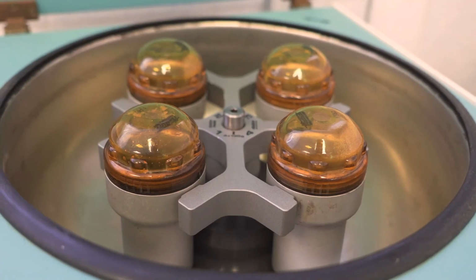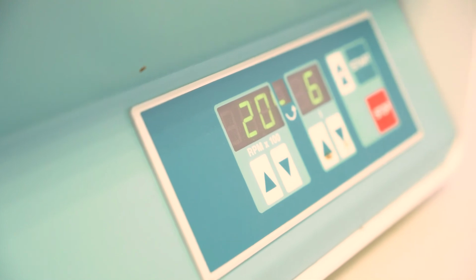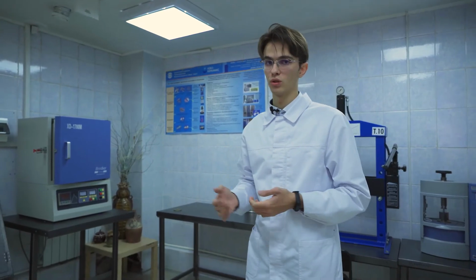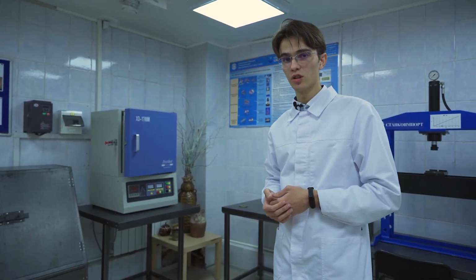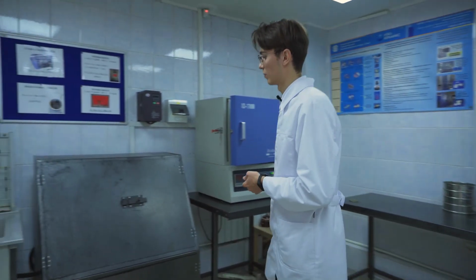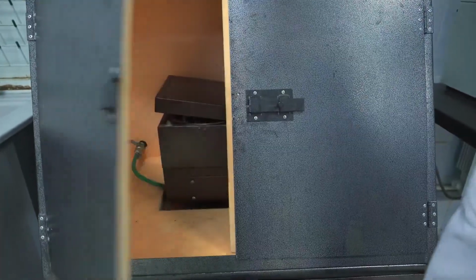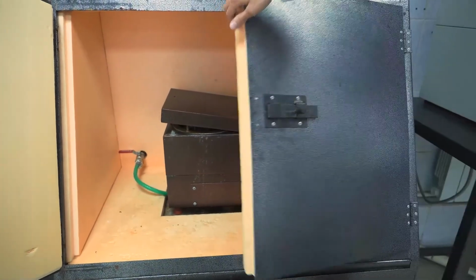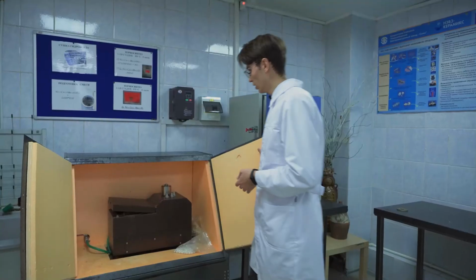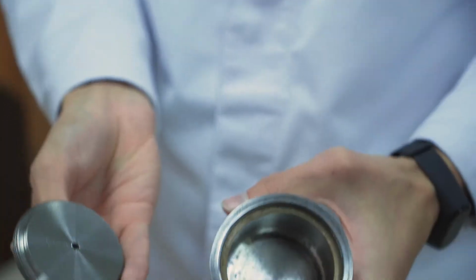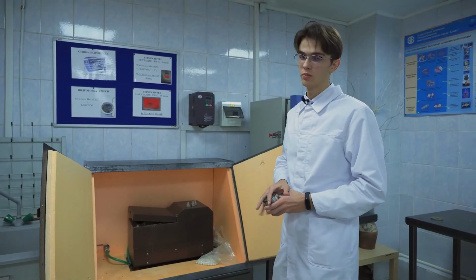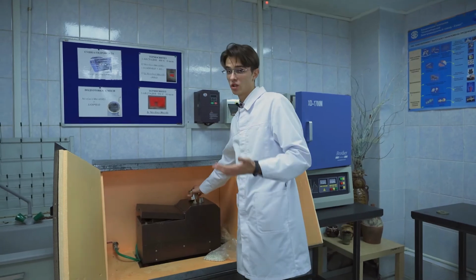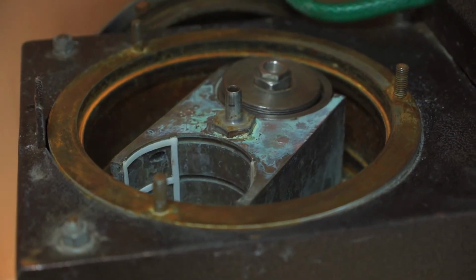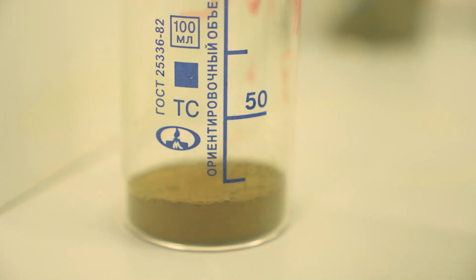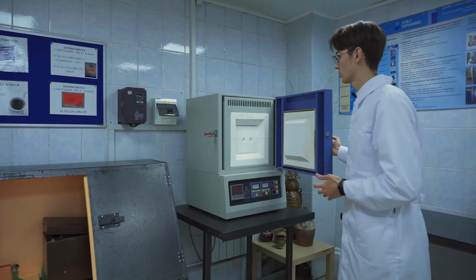Here we also do the synthesis, but in a different way. We grind the centrifuged and dried powder in a centrifugal planetary mill. Here it is. Beforehand, we mix the obtained powder with lithium hydroxide and put it in a box. In the same box, we put balls, which grind the material at a high speed. We take out the powder crushed, pour it into crucibles, and put it in the furnace.